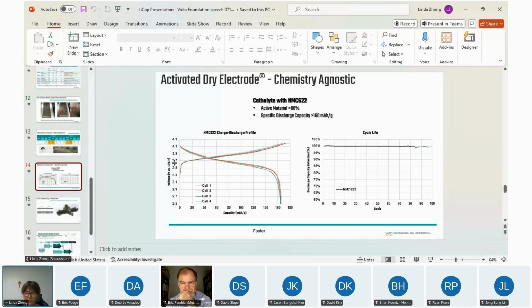As I said, I can make ultracapacitor electrode. I can make battery electrode. I can make solid state battery electrode. I can make sodium ion battery electrodes, right? So this is just an example. Like when we make the cathode in our dry room, our active material is 80%. This particular case is the NMC 622. This is NMC-based battery electrode. So you will see it's very stable. You see that at 100 cycles, your decay is very, very small, very stable, right?